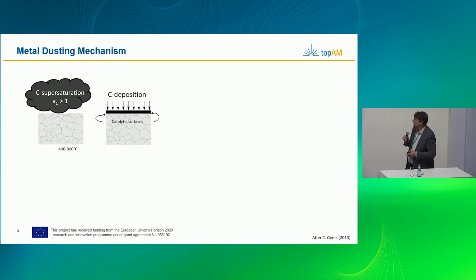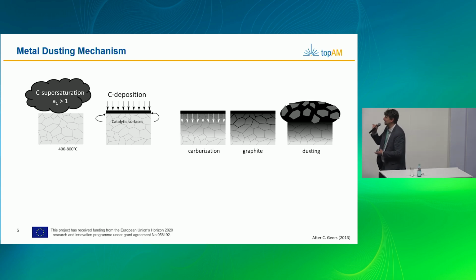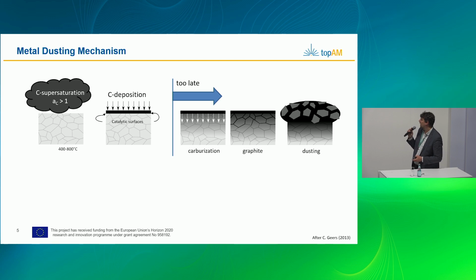I know that you are all AM experts, so I'll just quickly summarize this corrosion mechanism. You have this high carbon activity, and it wants to form coke. Maybe you have heard of carbon nanotube formation. That is also made out of this gas or similar gases, and it is basically the same mechanism. We form graphite in the material, and this eats up the material and turns it into dust. This is why the mechanism is called metal dusting. When this occurs, it's usually too late, because there is a long incubation time before the mechanism comes into place. Then in a few hours it can go millimeters deep into your material.